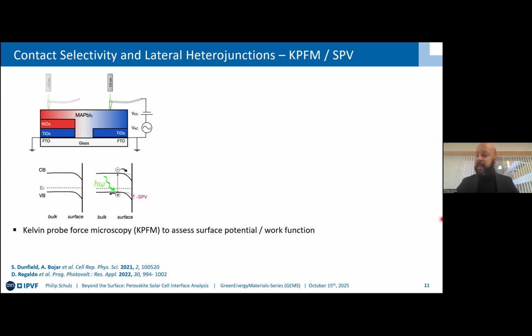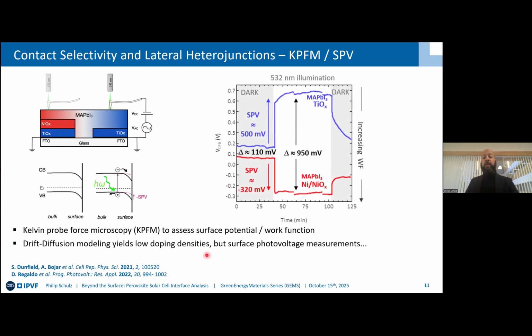And where it all stops being a complete picture is once you go to measurements that also involve the additional use of light. So going from Kelvin probe force microscopy measurements, that you can also use in order to map out the surface potential, to light-induced surface photovoltage measurements. And then you can make out a stark difference between the perovskite deposited on titanium oxide versus nickel oxide in the surface potential, a very strong jump that is actually not compatible with its completely intrinsic character of the perovskite or band offsets alone. So there need to be additional factors playing into this.